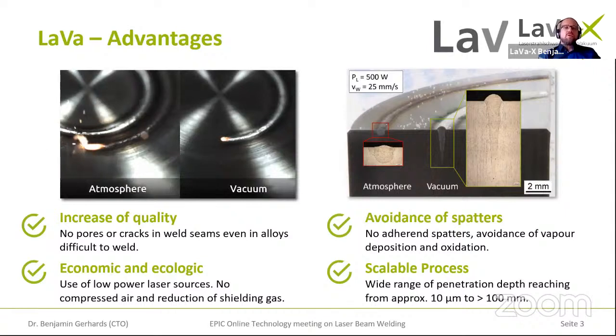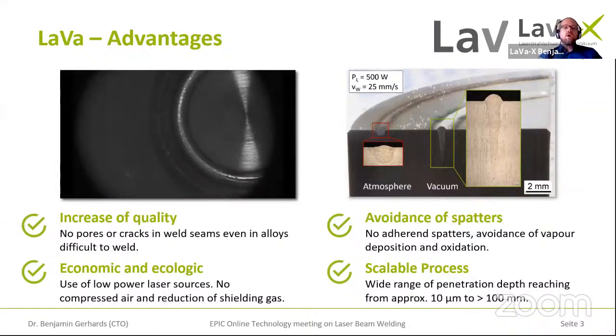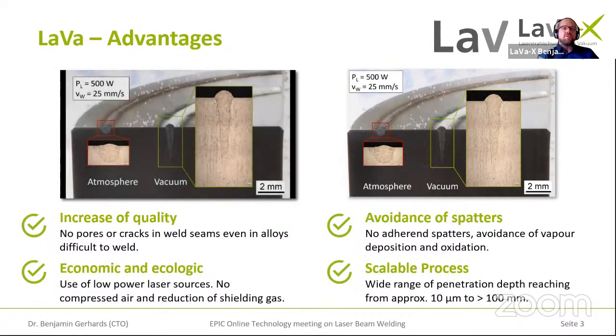For example, we have an increase of quality, so we have no cracks in weld seams, and this also applies for alloys that are difficult to weld, such as nickel-based alloys or aluminum-based alloys. And pores, on the other hand, are next to non-existent. We have the avoidance of spatters. If we have spatters, they are so tiny that they don't adhere to the surface of the weld. We have the avoidance of vapor deposition on the surface, and we have nearly no oxidization, or no oxidization. This is very beneficial in terms of welding, for example, stainless steel for fuel cells.